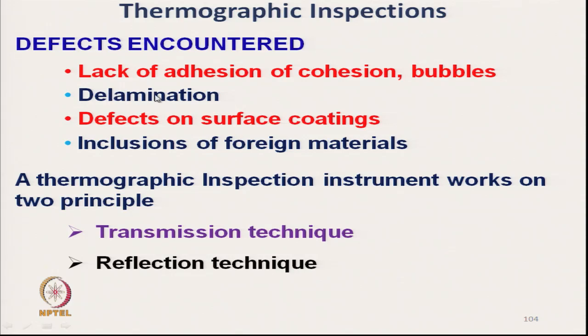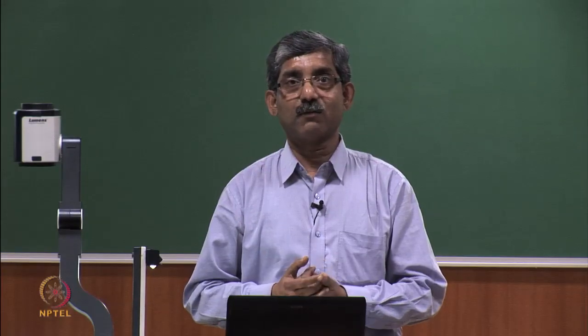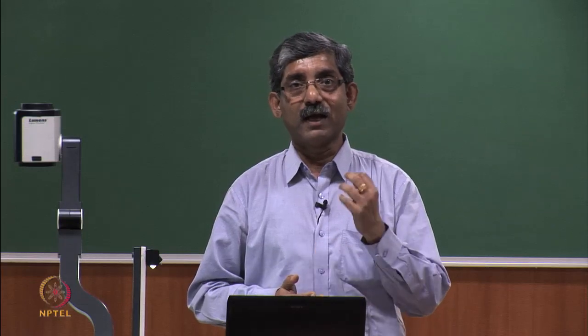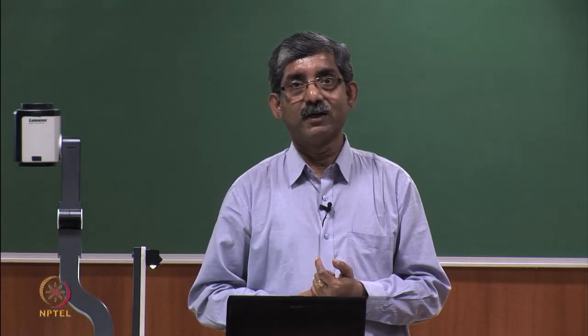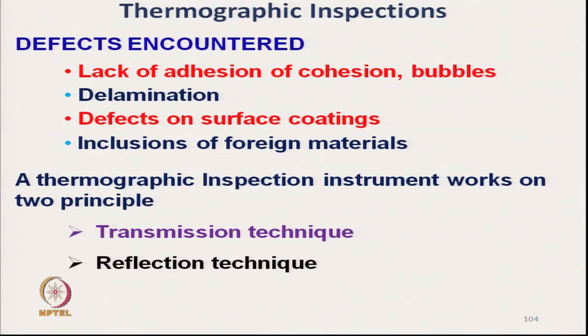lack of adhesion or cohesion, or bubbles. So, for this type of defects, bubbles present or lack of adhesion, we can measure using thermographic inspection. Delamination we can measure, defects on surface coating, and inclusion of foreign material in the composite material we can find by using thermographic inspection.